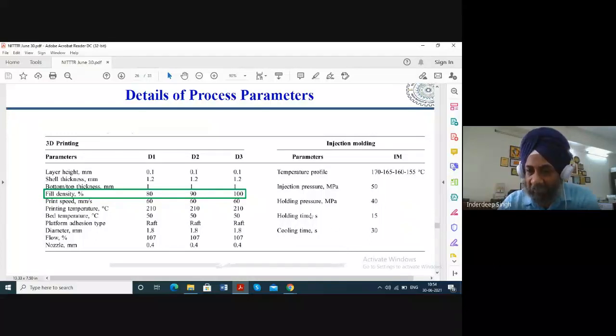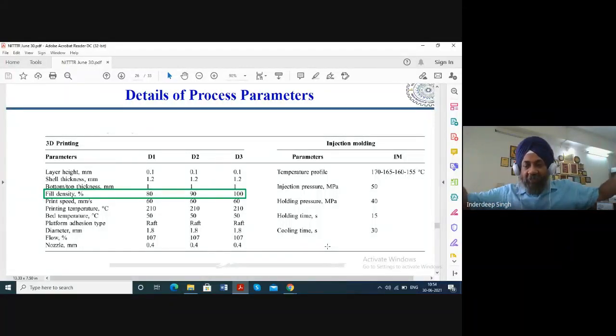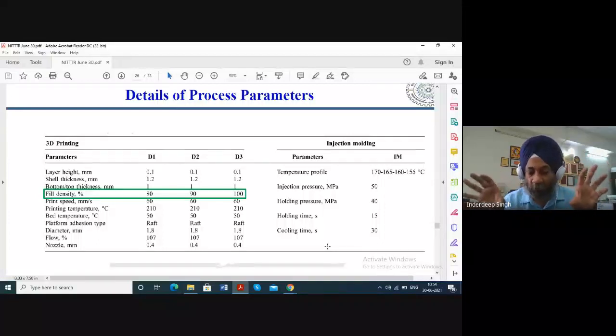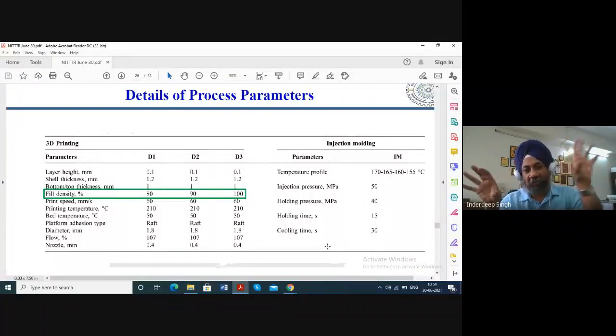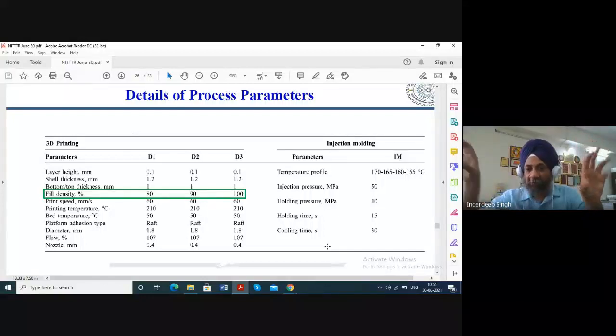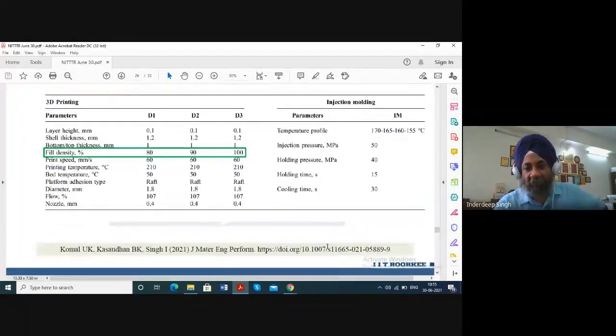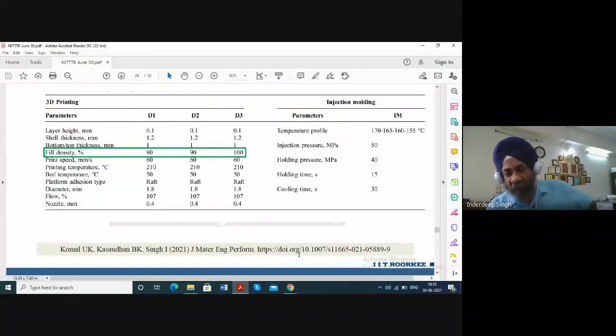And the parameters, as I have already discussed in the beginning, I introduced these terms. I have not explained in detail, but I introduced that these are the parameters which are used to control the injection molding process, like injection pressure, holding time, cooling time, temperature profile. So all along the barrel, we have to have a temperature gradient in order to get the right quality of the product. So both sets of parameters were optimized for both the processes, the FDM process as well as for the injection molding process. And then we compared, and this article, I already told you, is available now online.